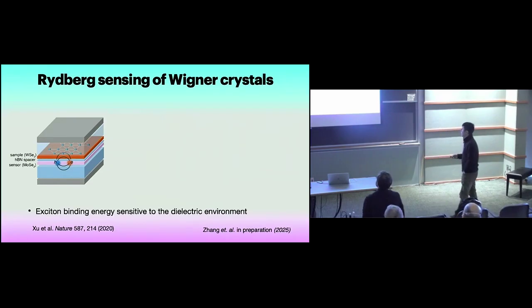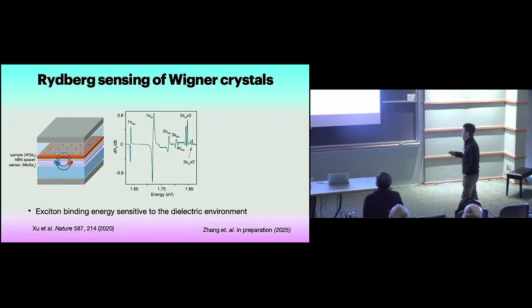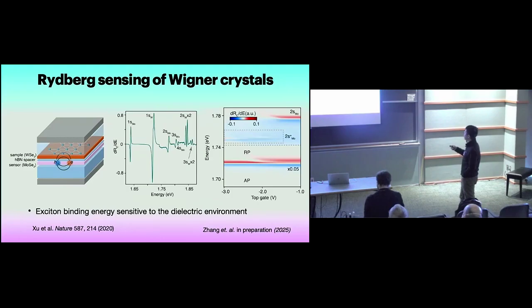Okay. So we do this type of experiments where we vary the density in tungsten diselenide, we vary the hole density, and we keep the MoSe2 layer intrinsic. So there's no charge variation in this MoSe2 layer. So initially we see that there are these Rydberg states. We can see very clearly 1s, 2s, up to 4s states of the exciton. And as we vary the doping level in the tungsten diselenide, you can see the repulsive polaron and the attractive polaron formation. The 2s exciton of MoSe2 actually shows some quite interesting behavior.